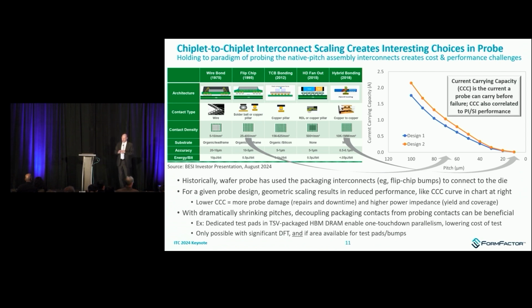So 75 micron pitch, and these are two probe designs, both utilizing the MEMS technology I referred to. All we're doing is scaling them in pitch. You see, not surprisingly, as I go to smaller pitches and therefore smaller cross-sections of the probe, it's simple math, right? If I have 10 micron pitch, I can't have a probe that's 40 microns across, otherwise it's going to touch two bumps at once. As I go from 75 micron pitch, I go to something usable. Around an amp seems to be a threshold that really creates reasonable production robustness.